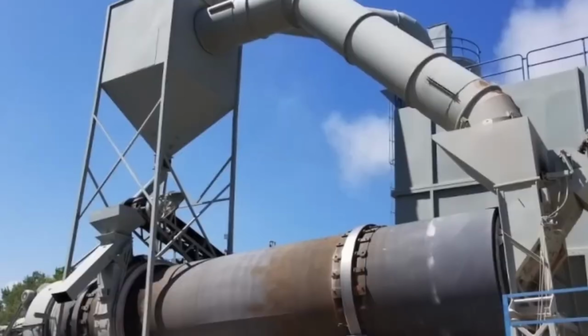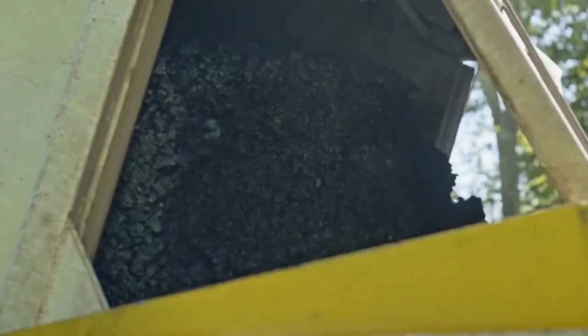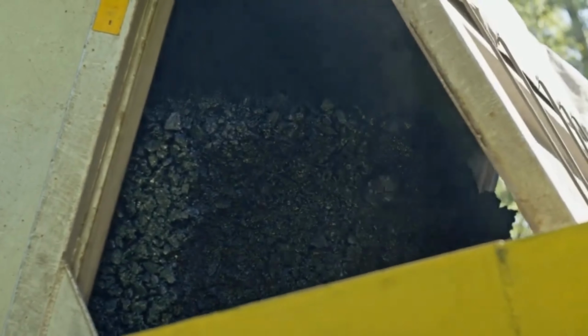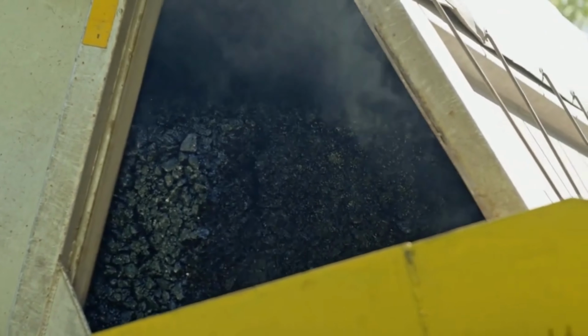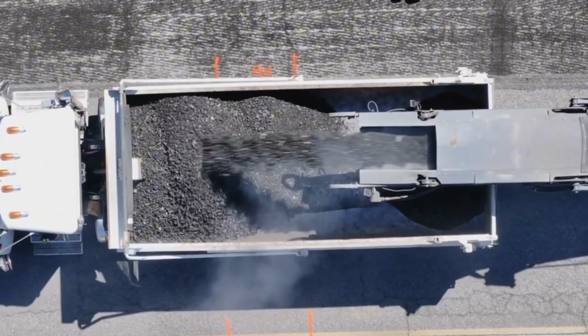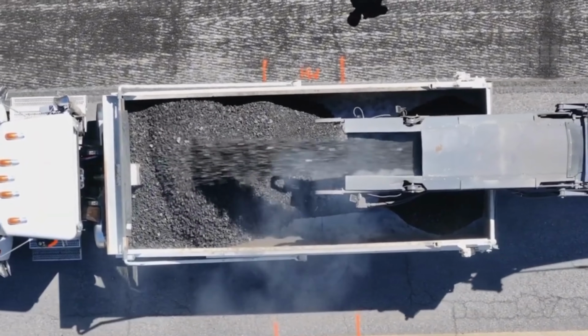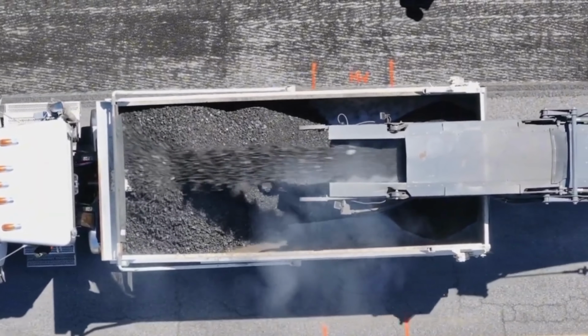In a drum mix plant, the process is continuous. Aggregates flow through one end of the drum while binder is injected midstream, coating the stone as the drum rotates. Either way, the result is a hot, black mixture at roughly 150 degrees Celsius, ready to leave the plant quickly before it cools. From here, insulated dump trucks line up beneath loading silos.